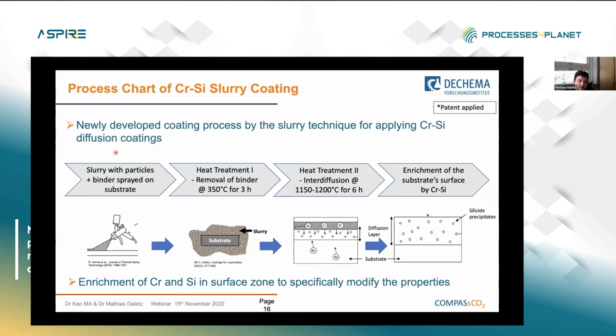The slurry coating technique has been around for years for aluminum systems. It's also commercialized and used a lot in the turbine sector, for example, but also in chemical process engineering. It's applied on large components like tubes. For chromium, the issue is that the melting point of chromium is way higher than that of aluminum, so we had to find ways to get around it, to make this possible as a slurry coating at, let's say, an adequate heat treatment.